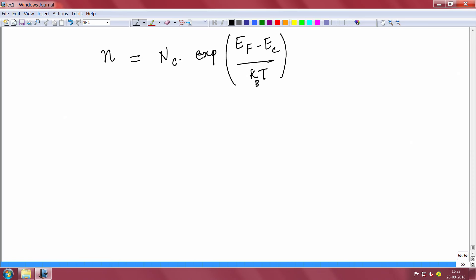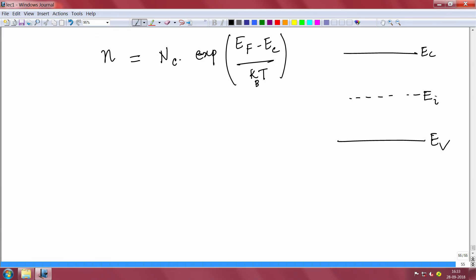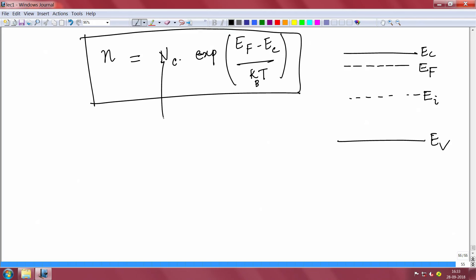To make sure we are not losing track, the number of electrons in a not-very-highly-doped semiconductor is given by n = Nc·exp((Ef − Ec)/kT). This is a very fundamental equation we will keep using. If the Fermi level is in the top half of the band gap, the semiconductor is n-type doped — more electrons than holes. If the Fermi level is in the bottom half, there are more holes — it is p-type doped. Nc is a constant that depends on temperature and effective mass. The electron concentration depends exponentially on the difference Ef − Ec.